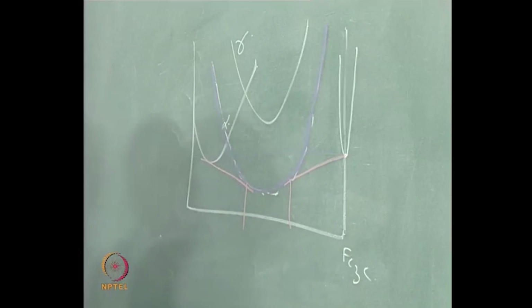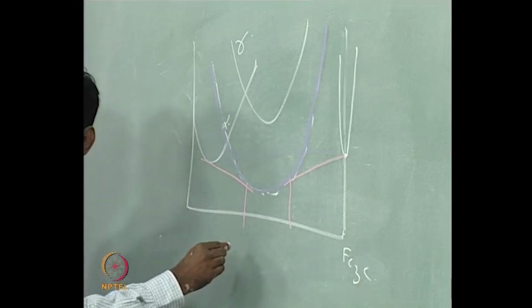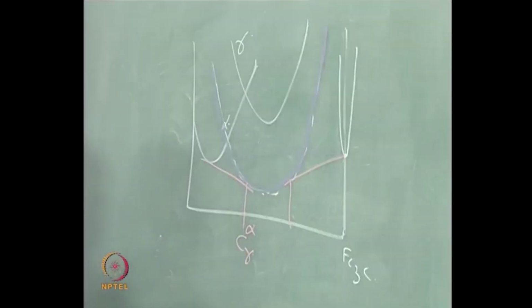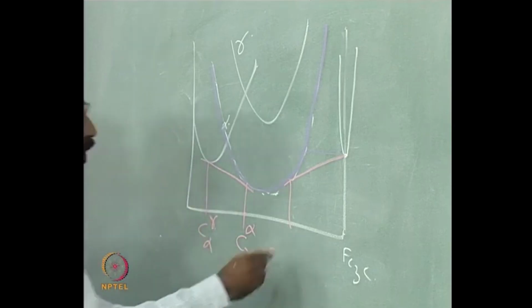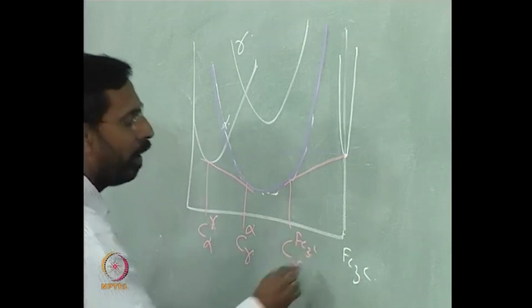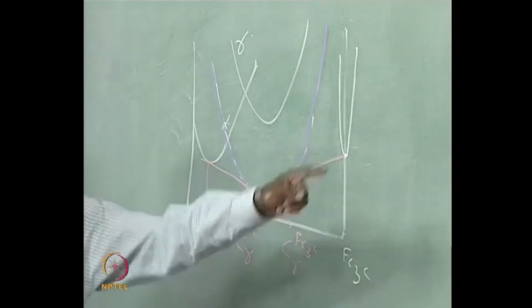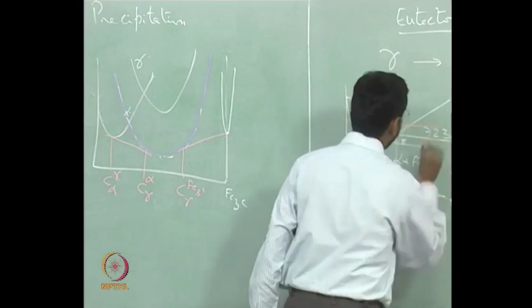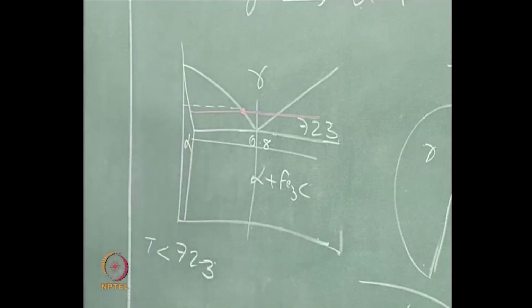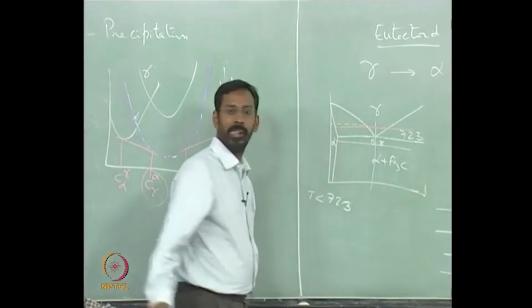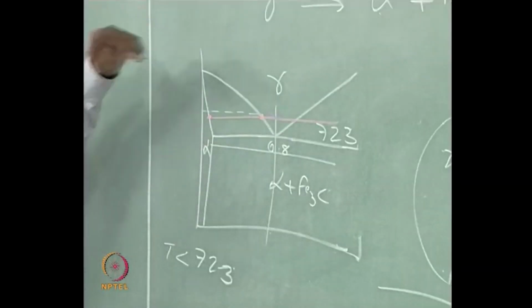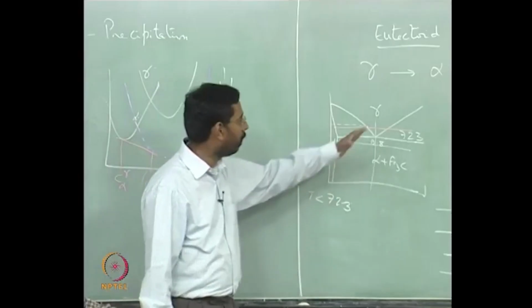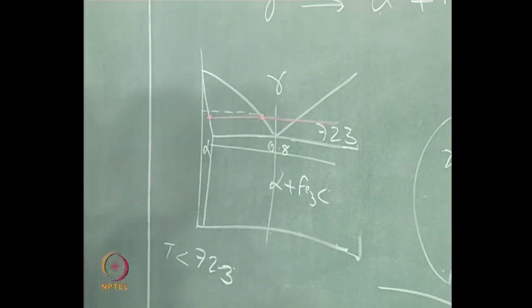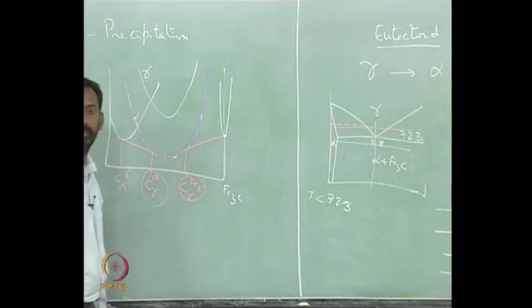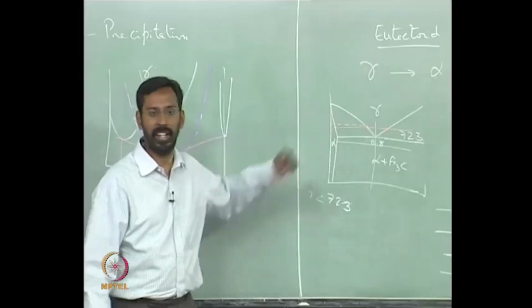these two compositions, if I say what is this composition, then this is the composition of gamma in equilibrium with alpha, and this is the composition of alpha in equilibrium with gamma, and this is the composition of gamma in equilibrium with Fe3C, and this is the Fe3C composition. And if I want to see these compositions at that temperature, I simply draw a line at that temperature, and this composition is what? C gamma alpha, that is this composition, and this composition is C alpha gamma. So that means this line is nothing but the locus of all gamma compositions in equilibrium with alpha, and this is nothing but the locus of all gamma compositions in equilibrium with cementite. So this point is nothing but C gamma cementite.